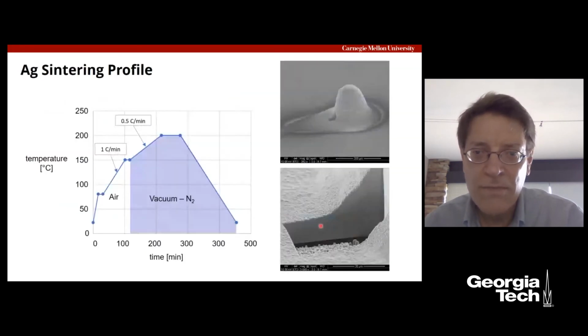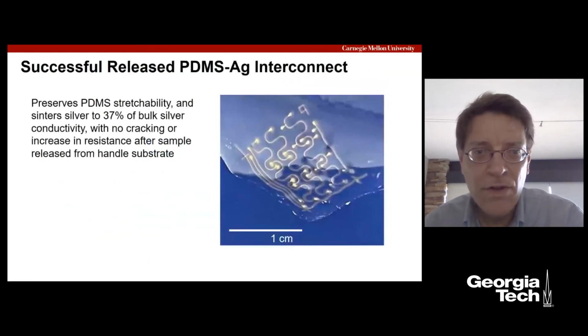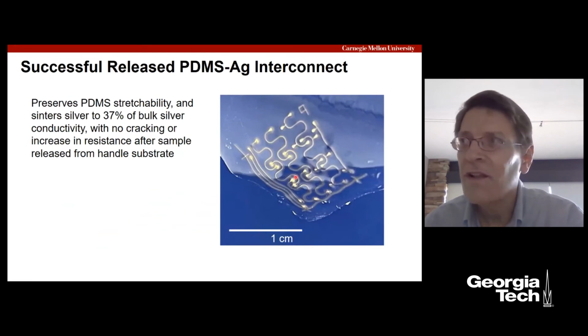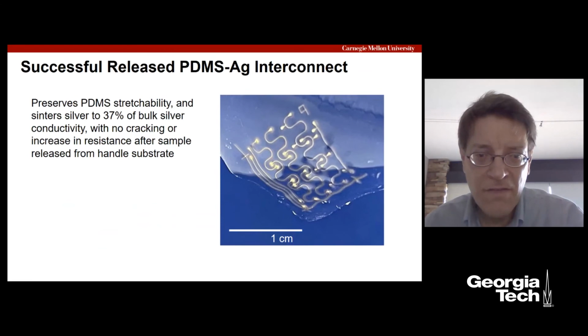Oh, and then you get some nice pictures. You can see the sintering of this. Here's an example pillar where, if you look carefully, there's a certain amount of porosity to this, but it's fairly well sintered, and we're getting good results. And this is a recent example of a released device.